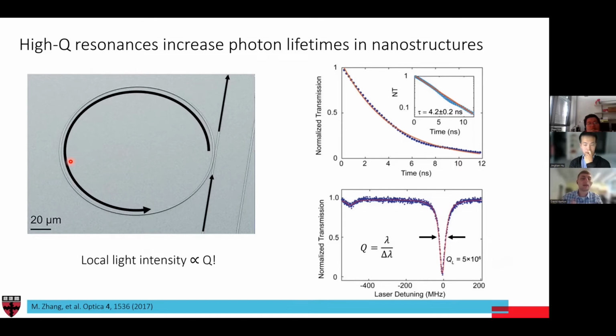And what that means is that the local light intensity will go up quite a bit because light is stuck in there for much longer. And so this light intensity is proportional to this quality factor. We can use this lifetime buildup to enhance the light matter interaction and allow us to do a lot of very interesting things.